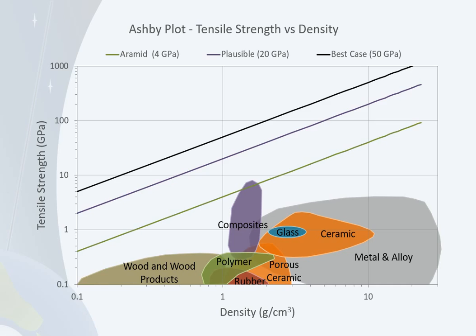Unfortunately, none of our conventional materials have reached our plausible threshold. So I'm afraid we're going to have to leave industry and head to the lab to find anything there. And we find 3 things to add when we move back into the lab space. Right at the top, very near our best case line, we find carbon nanotubes. Now, this shouldn't be surprising. We've talked about using nanotubes for space elevators for almost 20 years now. And that's because they have more or less the highest tensile strength ever observed by human beings.